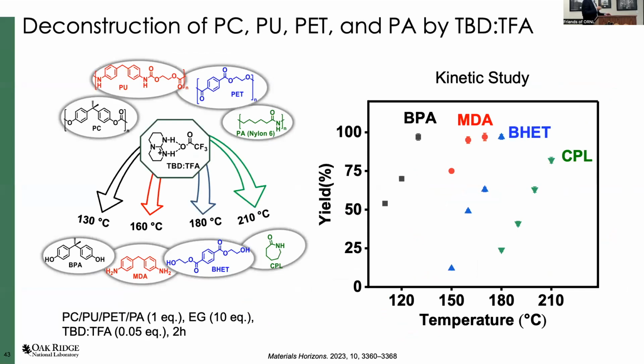More importantly, this can work on many different plastics. I showed the data of PET. This is the water bottle. This works for polycarbonate, like safety goggles, polyurethane, nylon, all of them. So far, this is the only catalyst that really works well for all of them. And also the beauty is the temperature is different. Polycarbonate is easiest to depolymerize. It happens at 130 C, almost full conversion. Polyurethane is next, this red one. Next is PET. Then nylon comes.